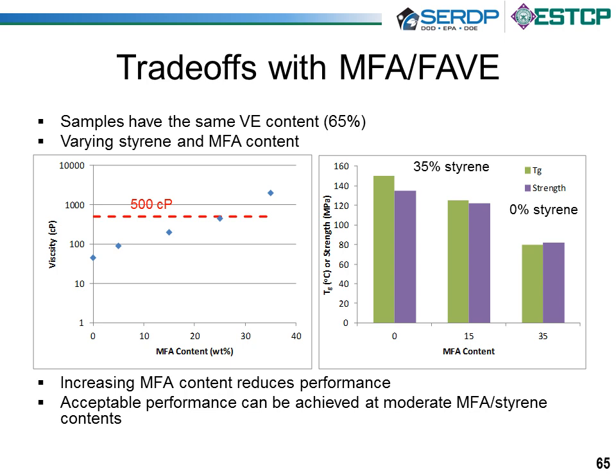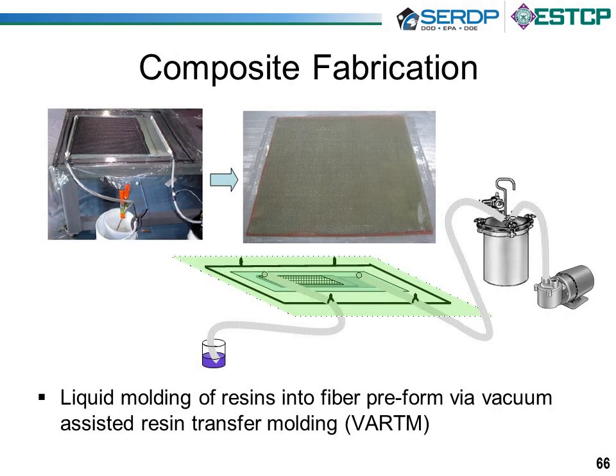We then made various composites from these materials using the VARTM process, which I depict here, and I'm not going to go into the details on that. But these simple composites that we made were for testing various properties like strength, modulus, short beam shear strength, and glass transition temperature, and a number of other properties. We measured this as a function of numerous reinforcements. We aged the composites, exposed them to fluids, did all sorts of weathering on these materials. And this is just a general summary of the results here.